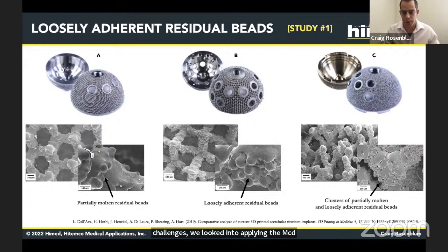and ultimately for an application like so, depending on the size of the bead as well as the size of the lattice, using a granular abrasive particle size range that was properly established was the way to go in being able to dislodge beads ranging from 100 microns size and downward.